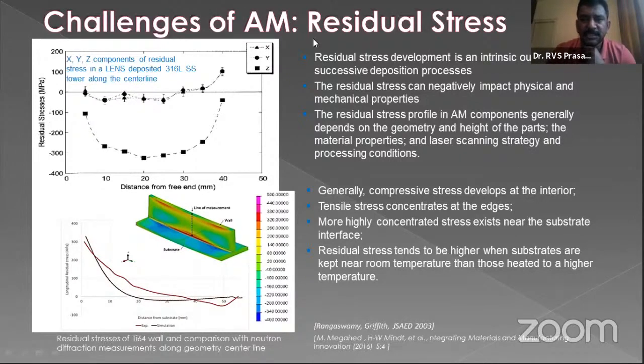And these residual stresses are also going to create a problem, because if you do not relieve the residual stresses and use the component for the final application, it may generate cracks or lead to premature failure of the component. So that's why residual stress determination is very important. Usually, after 3D printing, people will go for an annealing heat treatment, where all the residual stresses will be eliminated or reduced, and then the component can be dispatched for the actual application.